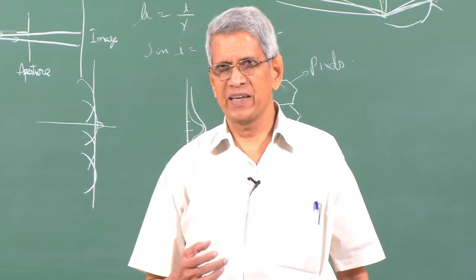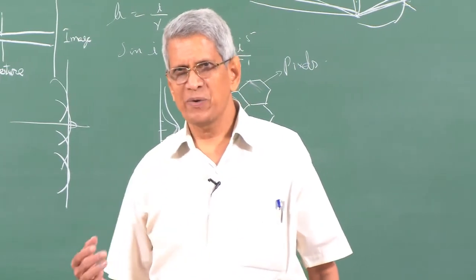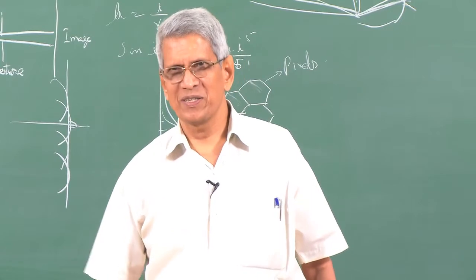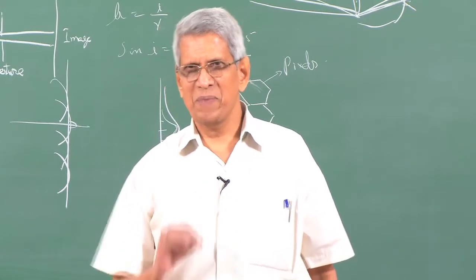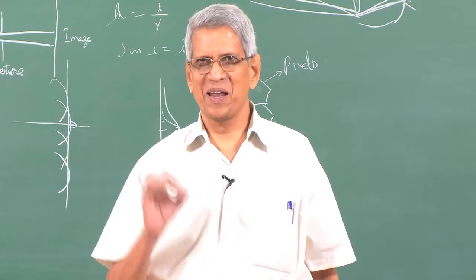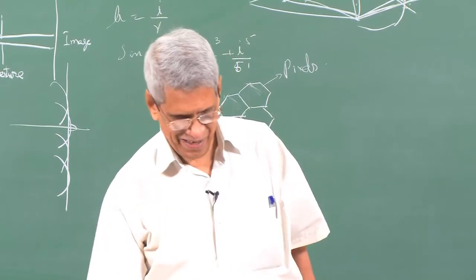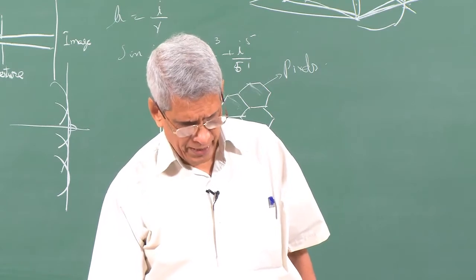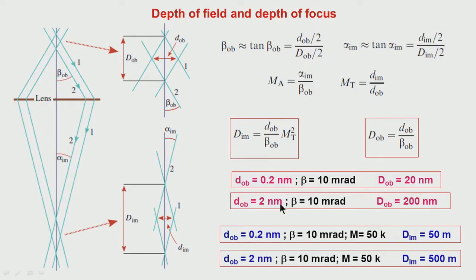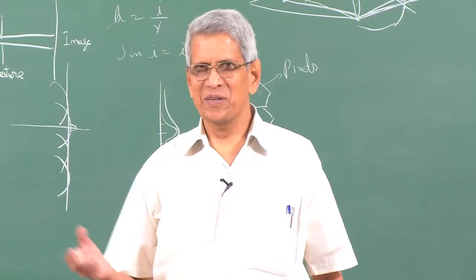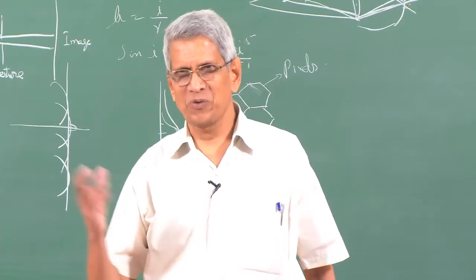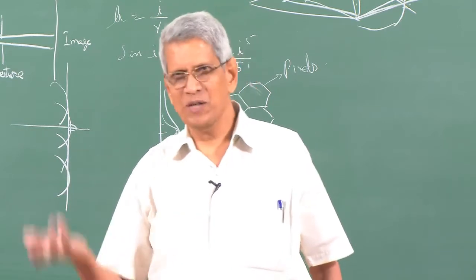Suppose the sample size is larger, the others will give a diffuse background and the contrast will become much worse. That means that when we want better and better resolution, the sample has to be thinner and thinner. That is the information. Okay. If I want about 2 nanometer, then this is about something like 200 nanometer. That means if I want to see a precipitate size of 2 nanometers resolved, not 0.2 nanometer, then I can use a sample which is 200 nanometer, 2000 Angstrom thickness or 1000 Angstrom thickness, which you can routinely prepare.